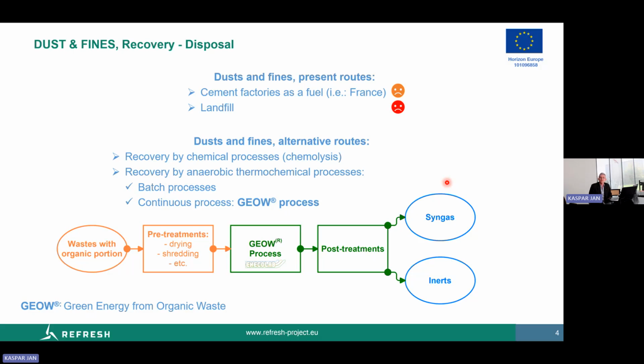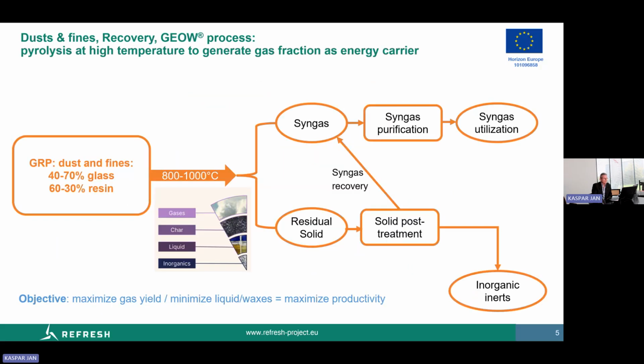Whereas syngas is a quite effective energy carrier, and this is what we want to do. The second aspect is that during this process we obtain inertization, so we can have even a toxic waste, which may end up possibly as a non-toxic waste, which can be discharged. So what essentially we do, as I said, is a high temperature pyrolysis.